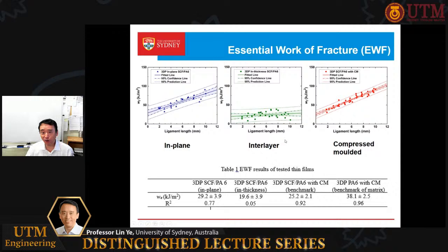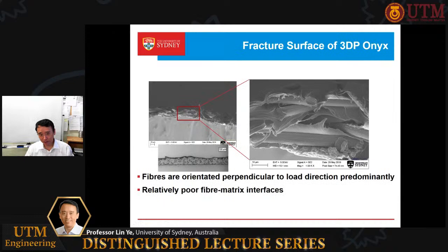But in any case, you can see this printing technique already differentiated the material fusion quality for the in-plane and the interlayer. Then the next step, what I mentioned, is you look at the microstructure of the fracture surface. You can see the interface is relatively poor. So eventually the short fiber reinforced nylon's fracture toughness is even not as high as the pure nylon.